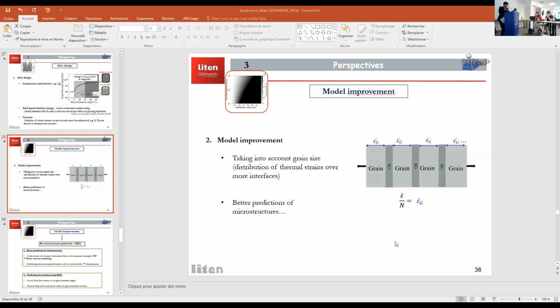So returning to the point, I think if we have smaller columnar grains which are growing, in this way we could identify that the strains acting over the entire region might be distributed into several interfaces. And this is what we think, that if we include this into the modeling aspect, we could take into account the grain size aspect. So this is what was your question? Yeah, in the process, in other words, could you imagine using grain refiners?